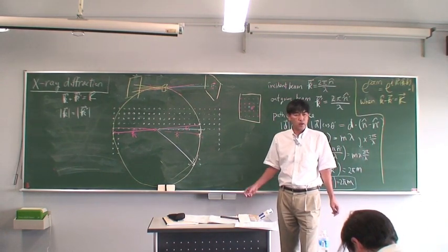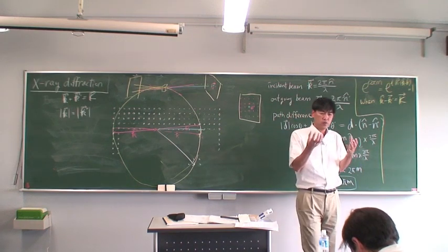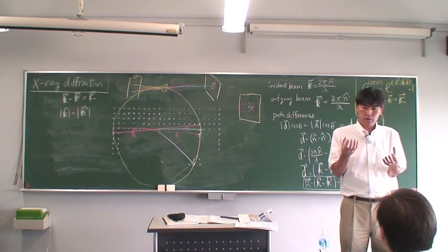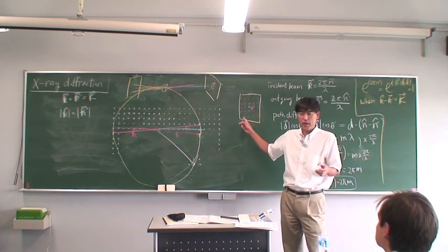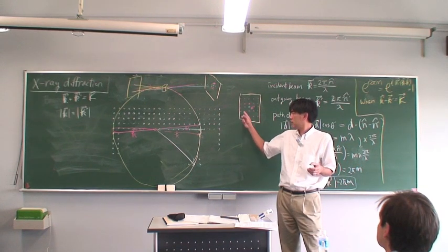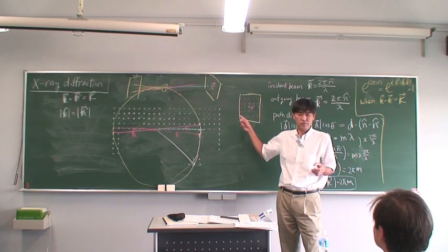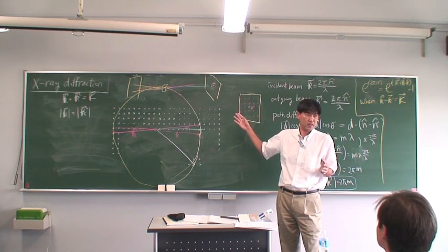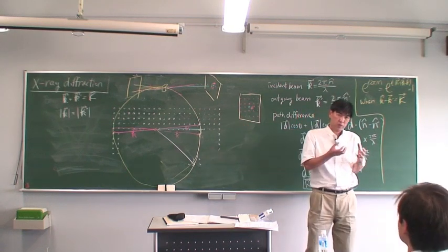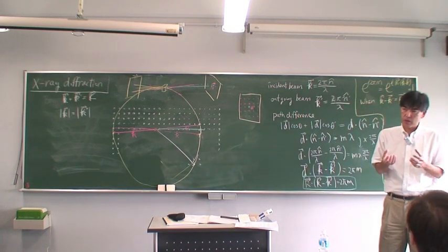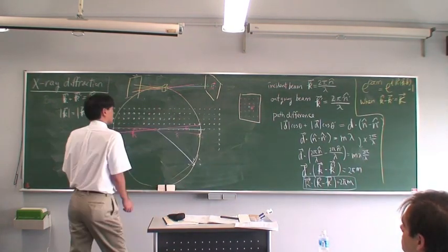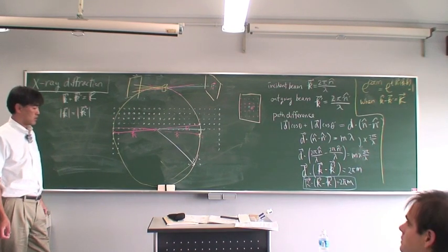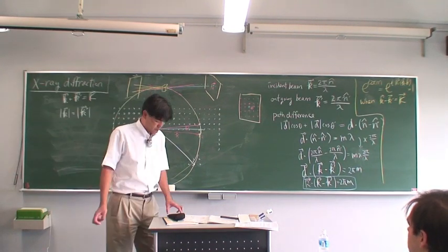Likewise, let's say you are given a sample with a strange, unknown structure. You perform X-ray and you get this kind of pattern. Immediately you know that, hey, this is like a simple cubic lattice or something else, but you get the idea. And this is how people determine structure of something using X-ray. So that's Laue's method. Okay?